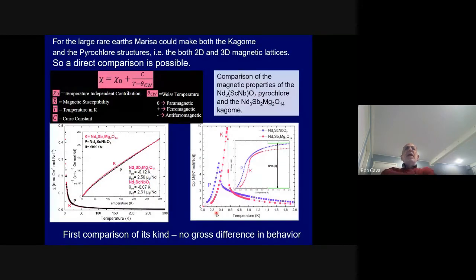Okay. So now if you can make this with different kinds of rare earths, if you can make the equivalent pyrochlore and the equivalent Kagome with the same rare earth, then you can do a test, and you can actually test whether the Kagome is more or less frustrating than the pyrochlore lattice. And that's what we did. And you can do it with neodymium only. Well, neodymium is one of the few rare earths that you can do this with.